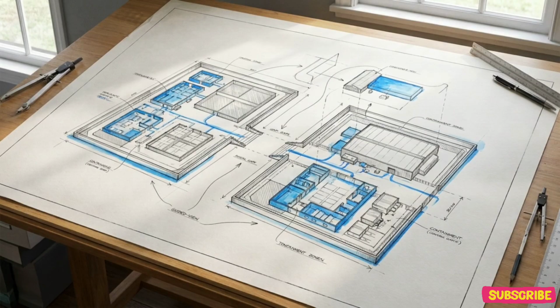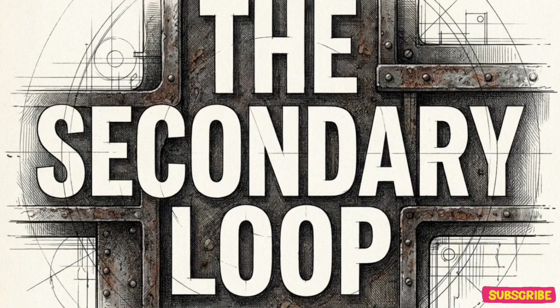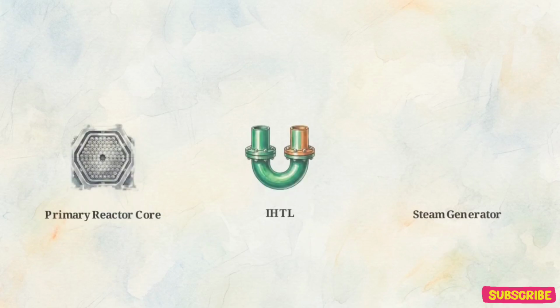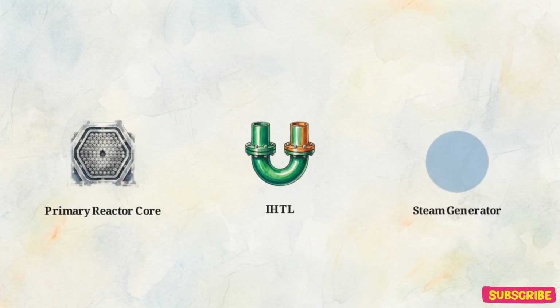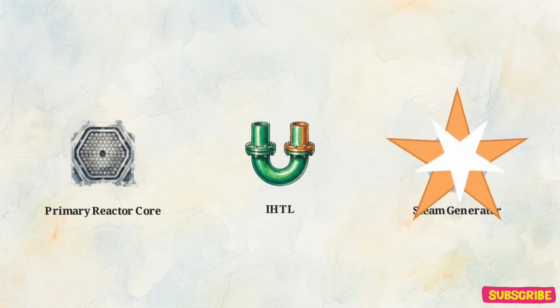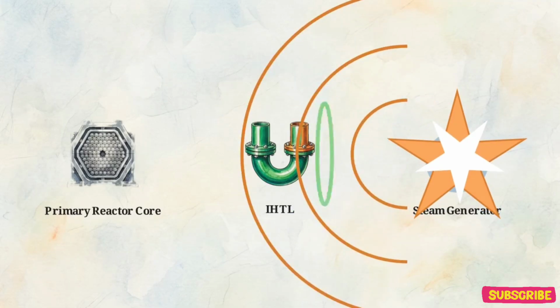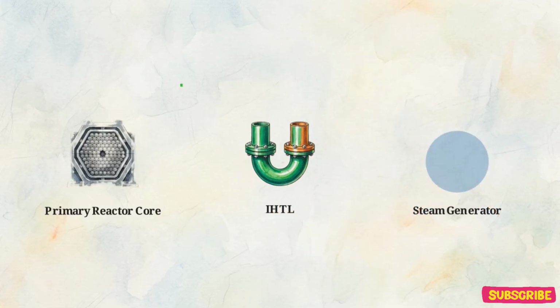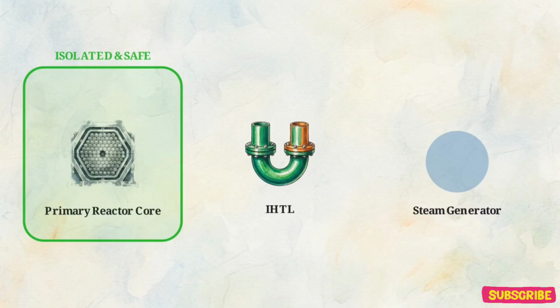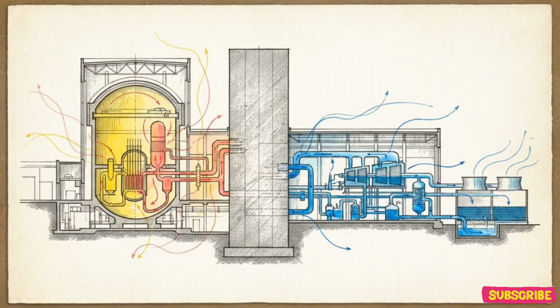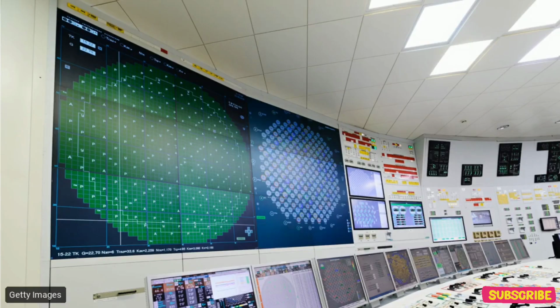When dealing with reactive liquid metals, relying on a single structural barrier is a mathematical risk the industry can no longer take. This disaster led to a permanent change in how sodium-cooled plants are built, centering on a new standard, the Intermediate Heat Transport Loop, or IHTL. The IHTL places a secondary, non-radioactive sodium loop between the primary reactor core and the steam generator. This physical separation guarantees that even if the steam generator suffers a catastrophic explosion, the concussive force cannot travel backward to damage the primary nuclear core.